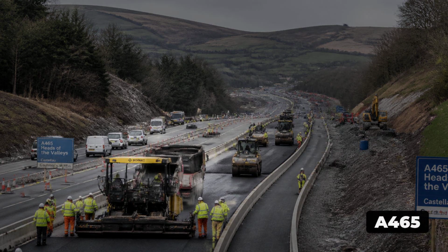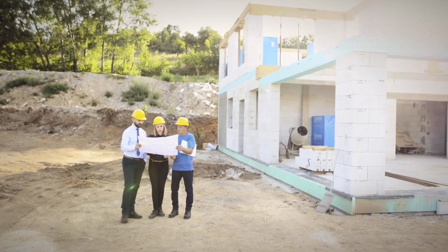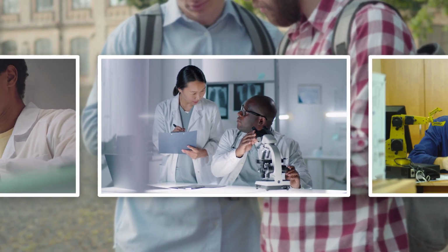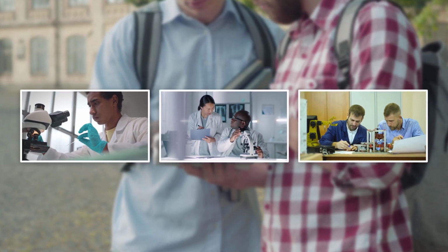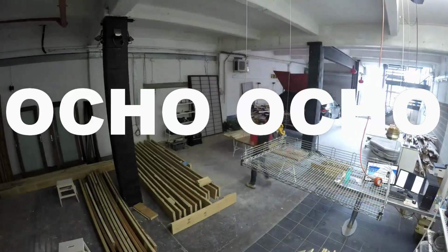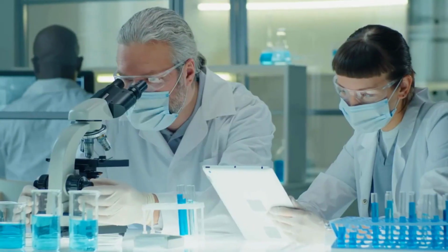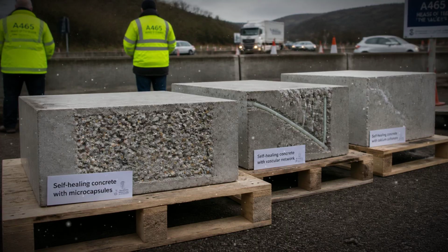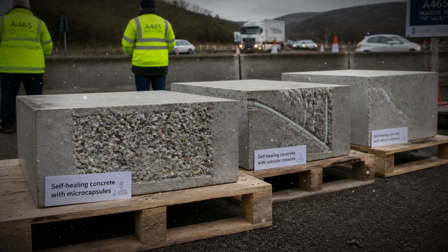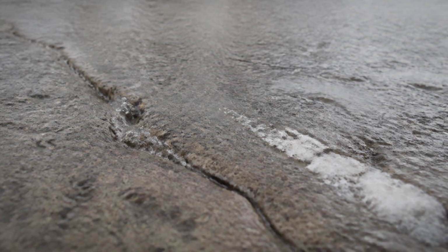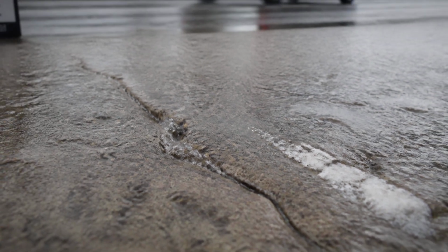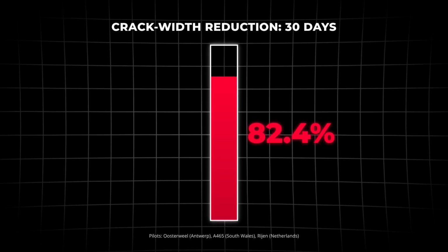In South Wales, the A465 Heads of the Valleys Highway upgrade became a live testbed for the Materials for Life Consortium, a collaboration between the universities of Cardiff, Bath, and Cambridge. Engineers cast 3 massive roadside retaining wall panels on site. One panel embedded bacterial spores, while others used microcapsules and vascular networks. When traffic loads and freeze-thaw cycles induced microcracks, environmental moisture triggered the self-healing process, reducing crack widths by over 80% within 30 days and preserving the panel's flexural strength.